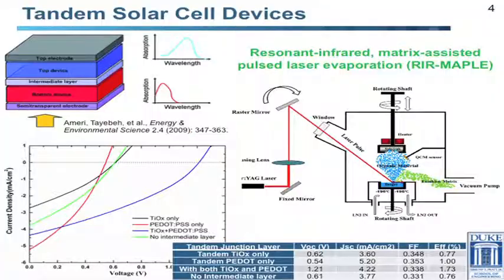So why is that? A tandem solar cell then is two different solar cell active regions that are stacked on top of each other, and there's this intermediate layer in between that's extremely important to the overall device performance. So while this has been figured out for these satellite systems, doing this in organic materials for terrestrial applications is challenging. So in my group, we're looking at this deposition technique. It's called resonant infrared matrix-assisted pulse laser evaporation. It's basically a laser-based deposition tool for depositing plastic films. It gives us much more control over making these devices and also determining what this intermediate layer is.